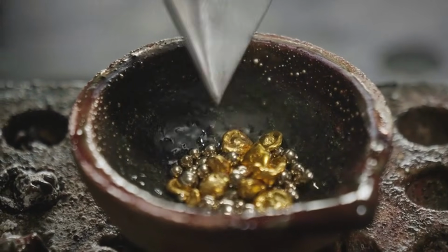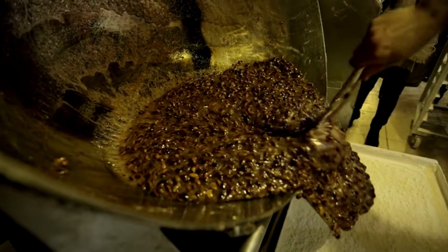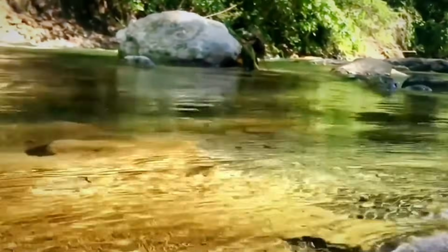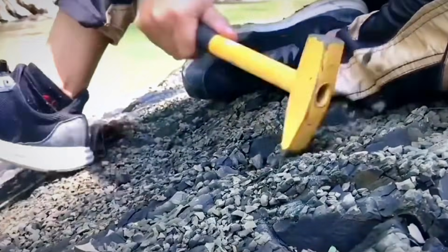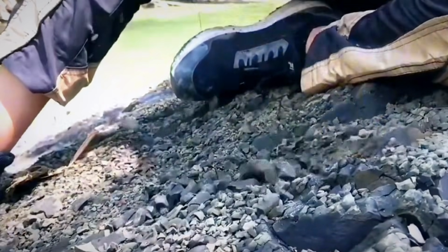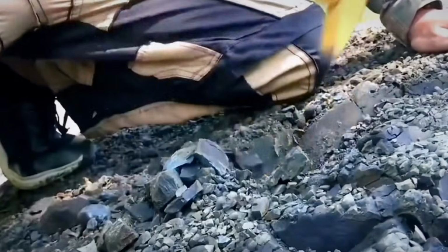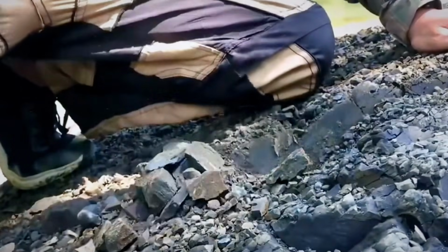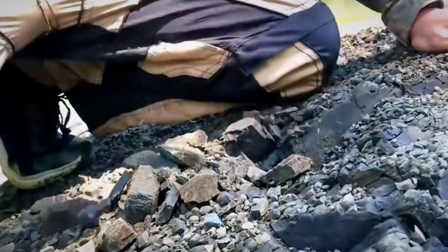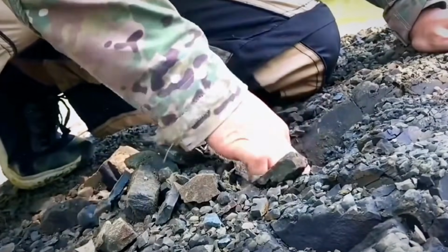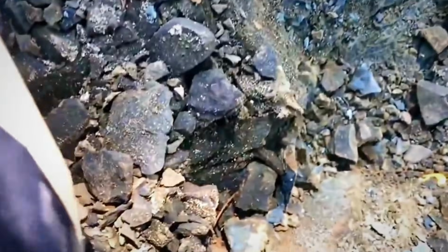The typical progression starts with a jaw crusher. This device mimics a powerful bite, clamping rock between a fixed and moving plate until it fractures. Output size from a jaw crusher can range from several centimeters to a few millimeters, good for field prep, but not yet fine enough for gold liberation. At this stage, larger sulfide nodules may still contain locked gold, and quartz fragments might be gold-bearing without exposing any metallic face.